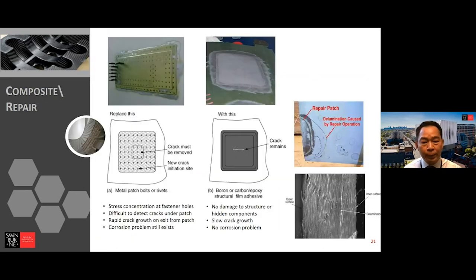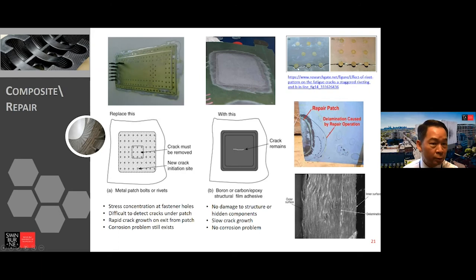So by looking at the traditional repair scheme, I worked in this area for 4 years after I finished high school, as a craft apprentice doing composite repair. I still remember that at that time we had to drill a lot of holes in the repair patch, and then bond it on the surface and use a rivet to put it in place. And there were still a lot of stress concentrations if you did not do it well, because when you put the rivet into the composite patch and into the structure, if you do not do it well, you will impose a lot of residual stress in the area surrounding the rivet.